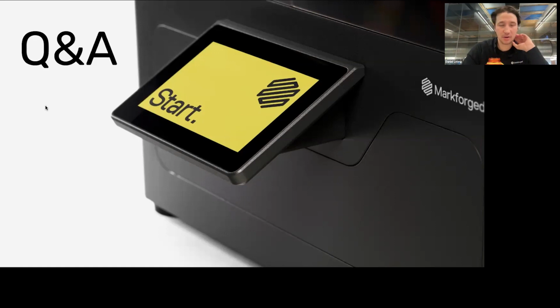Can you bend, crimp, and form copper after printing? Yes, to a degree. One thing I'll note is that MIM-based filaments, like any MIM, not just Markforged, result in parts that tend to be a bit more brittle than a standard wrought part. Elongation at break is a great example of how brittle a part is. Typically our elongation at break for post-sintered parts is lower than you would expect for a wrought part. So I would be a little worried about crimping, maybe bending and forming. You could probably do it, although you definitely want to test it out first.